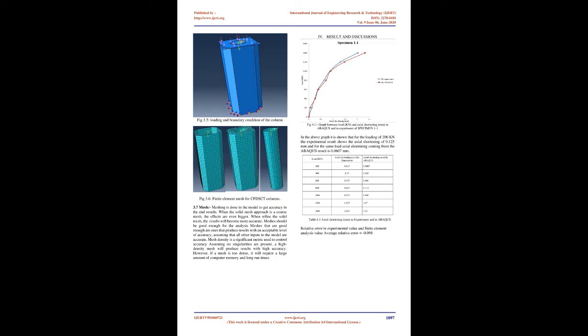Ren and Li, 2011, introduced a new type of composite member, a stainless steel concrete carbon steel double-skin tubular, DST, column. This composite member was expected to combine the advantages of all 3 types of materials, and had additional advantages of aesthetics and resistance to corrosion that outer stainless steel offers. A total of 80 specimens were tested. The main parameters of the tests were the sectional type, circular, square, rectangular, and elliptical, the column type, straight, inclined and tapered, and the hollow ratio of the composite section. The results showed that all types of columns behaved in a ductile manner, and the mechanical behavior was similar to those columns with double carbon steel tubes.